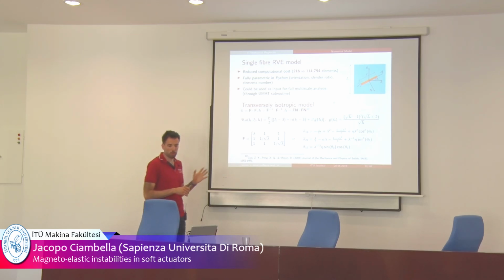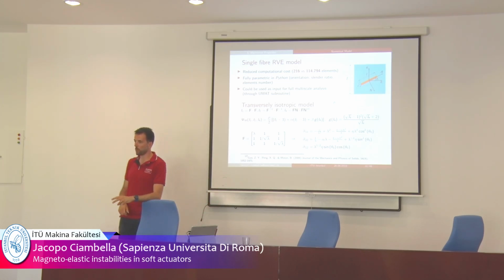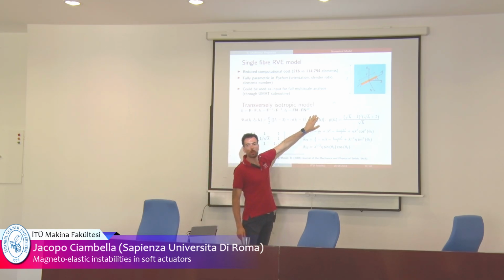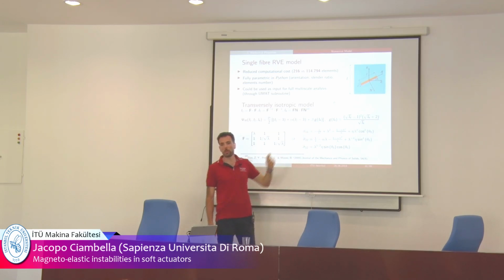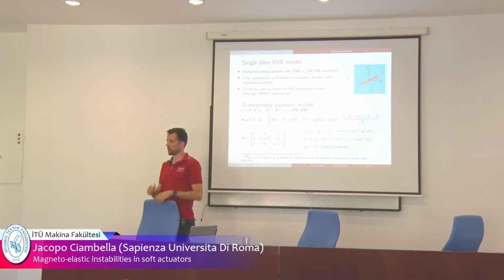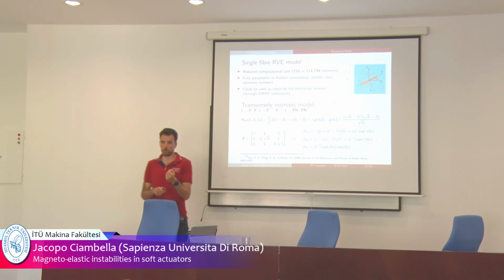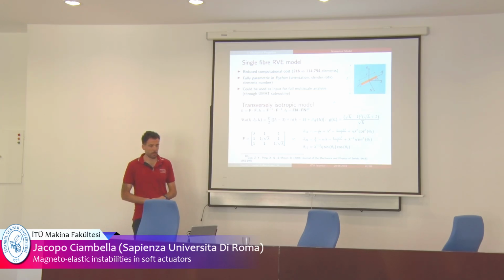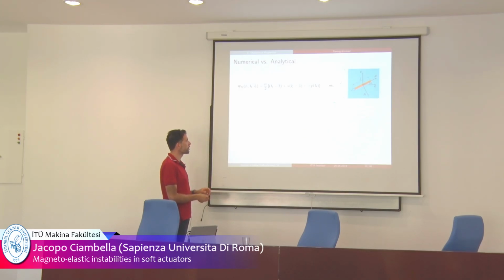The model at this level was compared with a standard transversely isotropic model. The energy of a standard isotropic model in nonlinear elasticity is this one. Essentially, you have these two terms, where I1 and I2 are the first two invariants of the deformation gradient. So this is standard isotropic nonlinear elasticity. And we have an additional term which depends on I4, which is the stretch along the fiber, how much the fibers are stretched. This is the elastic energy. You impose this form of the deformation, which is simple extension, and the fact that the determinant of F is equal to 1 is because the matrix is incompressible. That's the incompressibility constraint. You can work out the stress in closed form, and then you can compare this numerical simulation with this analytical model.